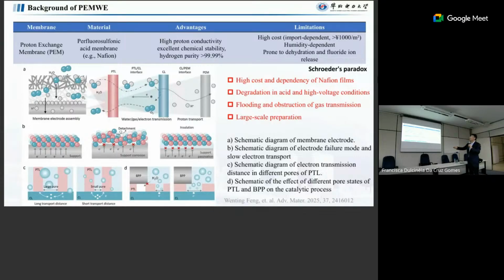And here, in this paper, we can see this is the catalyst, and here is the wall from the PTL. For example, if we have a large space compared to a small space, then we have an electron conductivity issue, because electrons need to be conducted into these catalyst layers. But the catalyst itself is not a good material for electron conduction. That means we need to sort out this space. The smaller is better, and the larger is not good. But the problem is if the space is too small, we will have problems for the oxygen transport and also for the water two-phase flow. Another issue is, if this is too small, the bipolar plate can cover this PTL area. The water cannot go in and the gas cannot go out. So we have a lot of issues with mass transport.